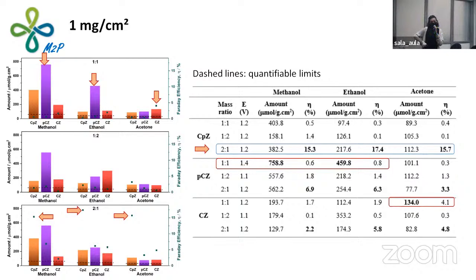But for CPZ, we were able to achieve 15.3% Faraday efficiency for methanol, 17.4% efficiency for ethanol, and 15.7% for acetone. Because of that, we chose the 2:1 ratio to proceed with this study.